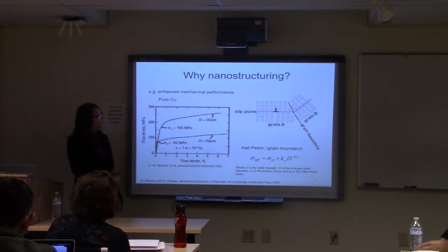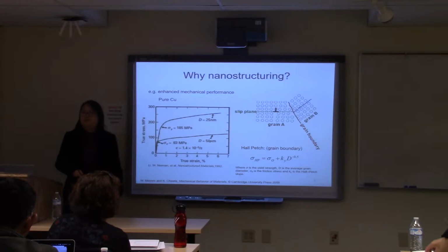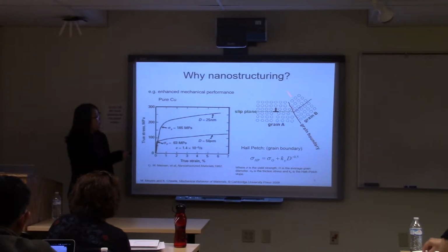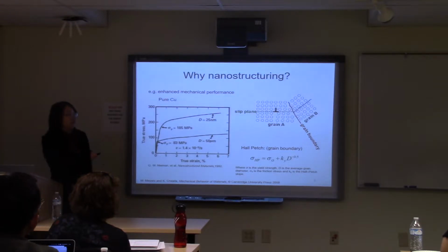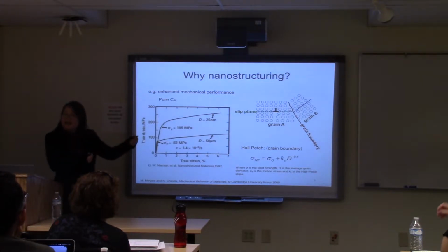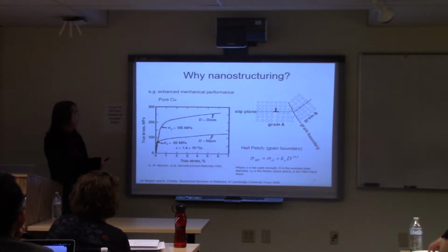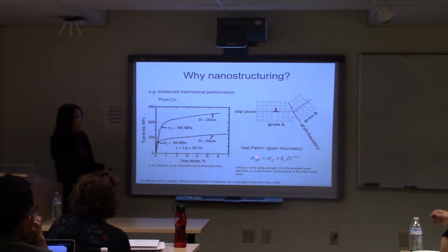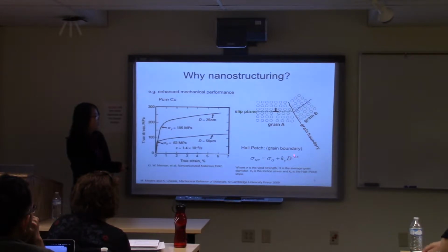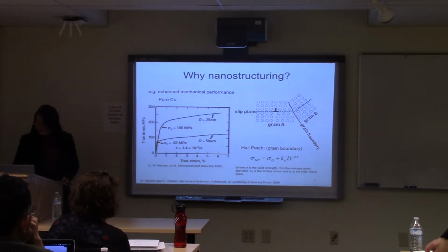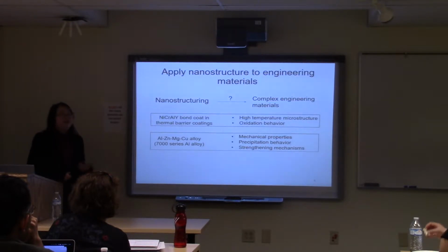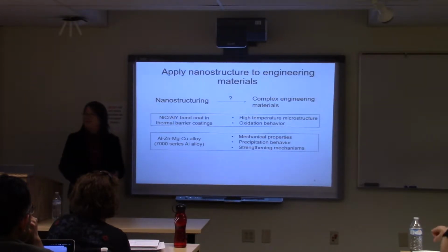The mechanism is very well established: the grain boundaries help to stop the motion of dislocations, so you need to apply higher stress to really deform the material. It's governed by the Hall-Petch relationship, where the strength is inversely proportional to the grain size. But in reality, most engineered materials are not pure metals.